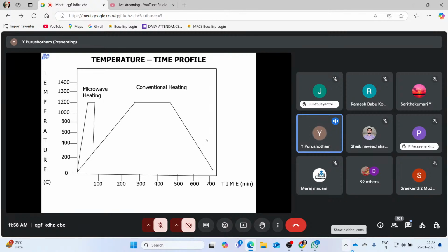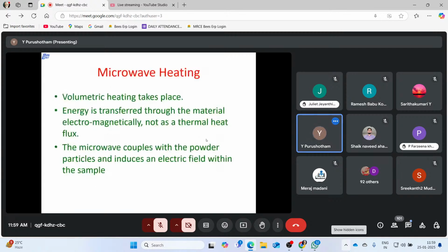Compared to that, in conventional heating we have to keep the material for some hours, maybe 3 to 4 hours, 5 hours, depending upon our application. Whereas in microwave heating, it will be in minutes only, from 1 minute to 10 minutes. You can make a comparative study between conventional heating and microwave heating. So there are a lot of advantages.